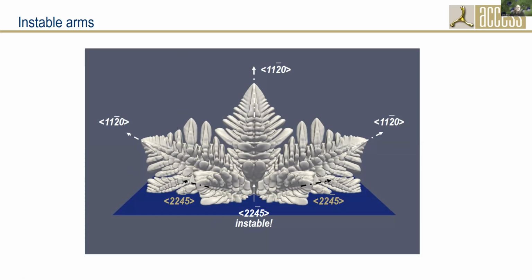You may ask if this anisotropy function is directly imposing the mode. It is just giving a favored direction, but it does not mean that if there is a maximum, there must be an arm. Depending on the process conditions, these arms cannot form because the conditions are not good. Under different conditions, these arms may form and even become dominant, if you run the same simulation with different process conditions.